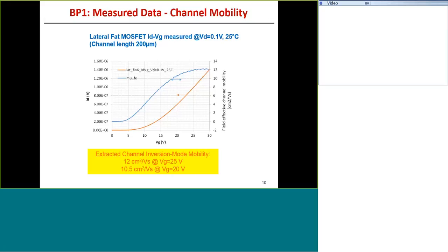Now, in many efforts to make good channel mobility, it is found that the channel mobility peaks at the threshold and then goes down rapidly at the point of gate bias in the on-state. And the on-state gate bias is nominally in the 20 to 25 volt range. So we prefer to have a mobility that peaks at that kind of voltage so that we get good on resistance in our devices.